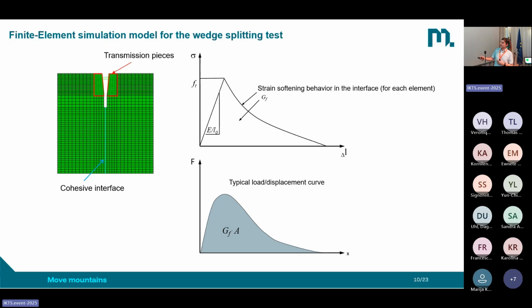So we assign this behavior to these cohesive elements here in the symmetry line, where we say, okay, when the stress increases, then we have a strain in these elements, we reach a maximum strength, and afterwards we have a softening behavior. The area here under this curve is the specific fracture energy. So this means we can then simulate a crack propagating through the sample and receive a load displacement curve, as you see it here, where we have this maximum load, and then the area under the curve is represented by the work of fracture. It means G_F times A, specific fracture energy multiplied with the cross-section area. What I would like to mention here is, even if we have this peak for the single elements, in the end, the summary of the fracture of all the elements gives a curve without a sharp peak.